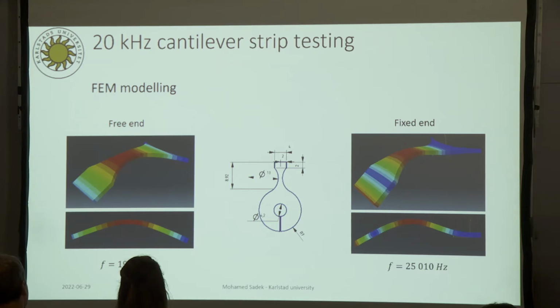And yet it worked. We did produce fatigue data without knowing the stresses. So how is that possible? For those of you who are used to the ultrasonic fatigue testing system, you should know that every part of the system has to have an individual resonance frequency at 20 kHz, but this specimen does not, and it works anyway. That is explained by the fact that the specimen has a mass so little compared to the rest of the system that its frequency does not affect the frequency of the whole system. The specimen is so small that it's forced to follow the system, even though it's outside of its own resonance.